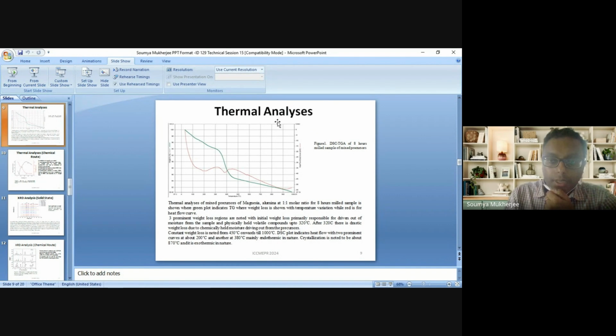Moving on to the thermal analysis part, that is the thermal analysis for the milled process, the modified solid state. It clearly indicates that the crystallization zone is below 1000 degrees and is coming close to 870. In general, in the crude solid state process, the crystallization is around 1200, which is much higher compared to the modified solid state process.